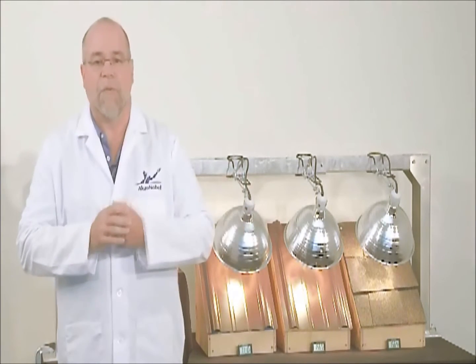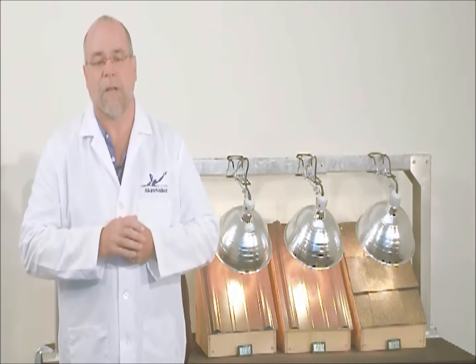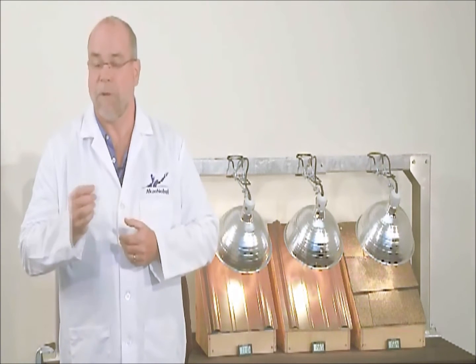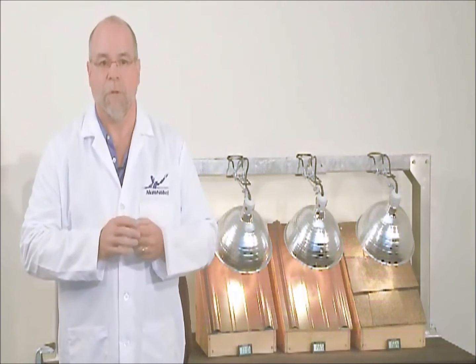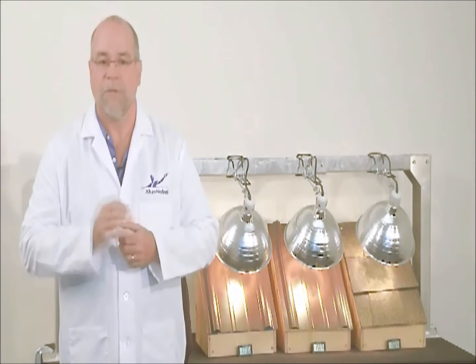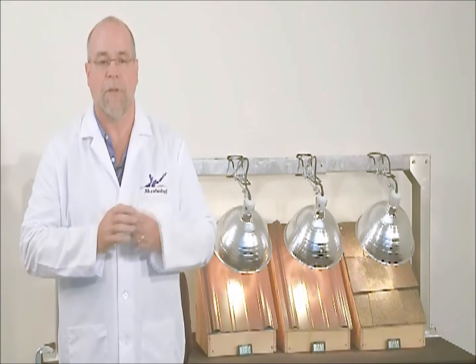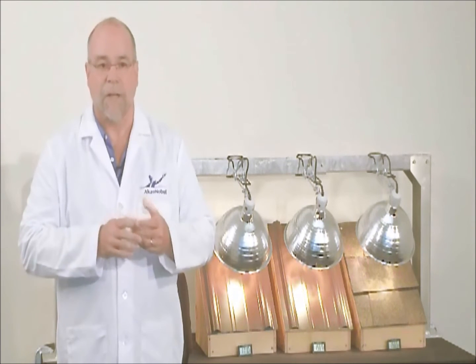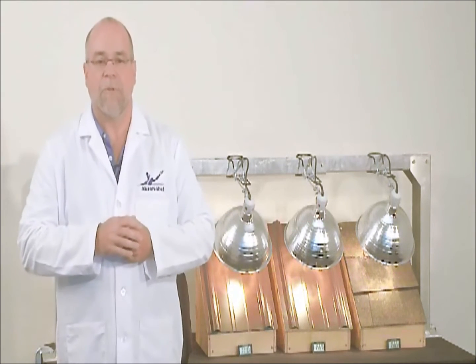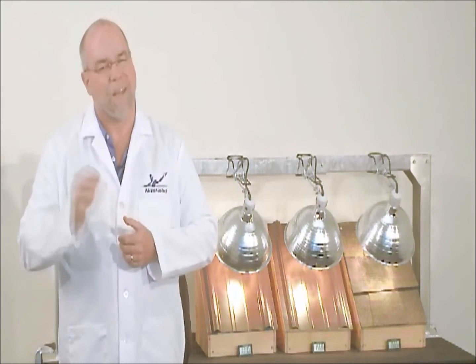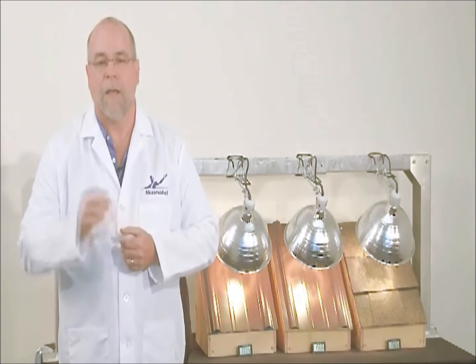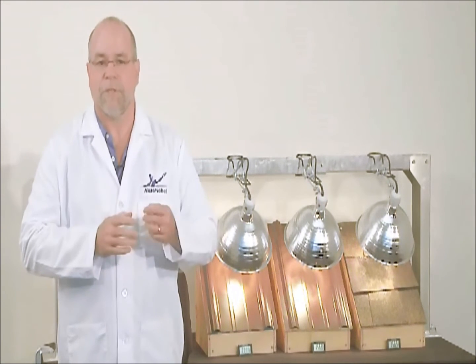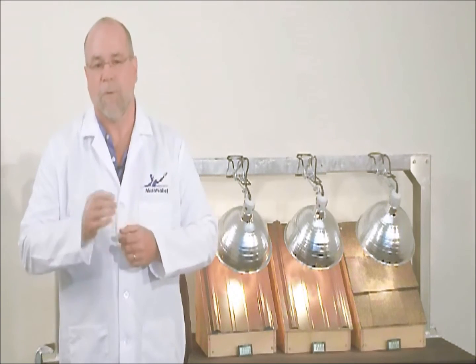Starting on the left, we have a brown metal roof with Cool Chemistry technology that registers a solar reflectance reading of 26%. The middle unit represents the same brown color using standard pigmentation with a solar reflectance of 10%. Finally, on the right are standard asphalt shingles that have a solar reflectance rating of about 10%. Each of these materials have been subjected for several minutes to the same type of heat lamps we use when evaluating surface temperature.